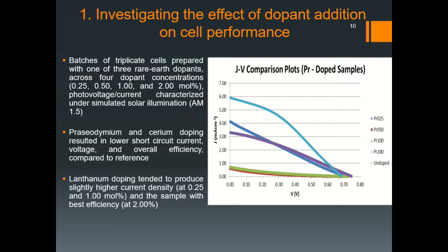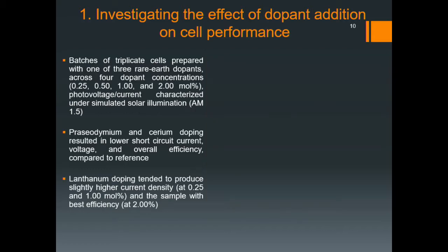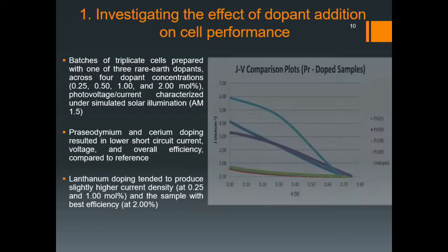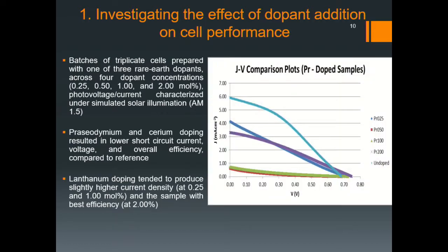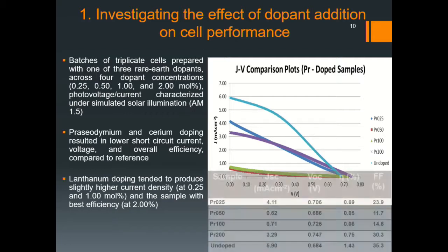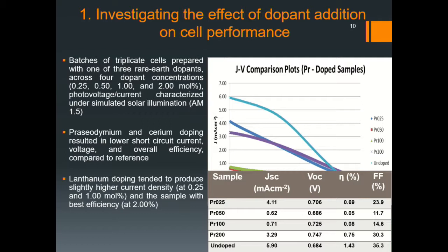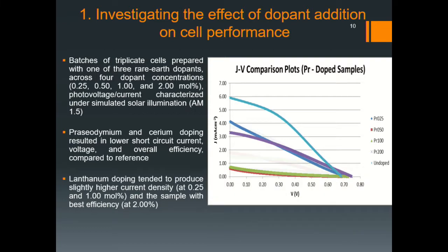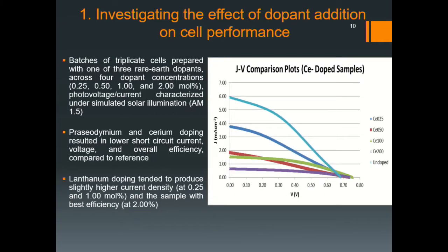Basically, the higher up the curve meets the x-axis and y-axis, so this point right here and this point right here, the better the cell is performing. And the further the curve is pushed towards the upper right, again, the better the cell is performing. So for praseodymium and cerium doping, we essentially got lower performance. The cell current, the cell voltage, and overall efficiency dropped compared to the reference. This is for praseodymium, and this plot is for cerium. So our reference is up here, and our doped samples are down here.